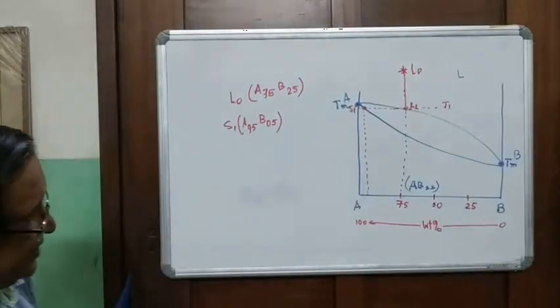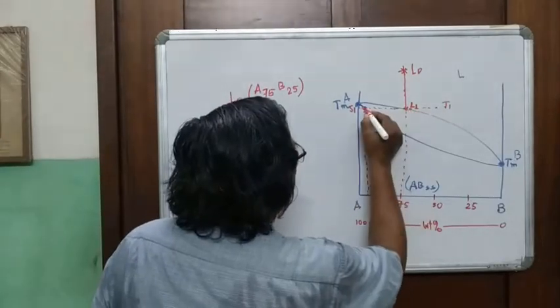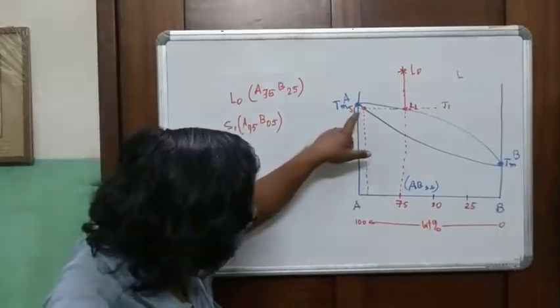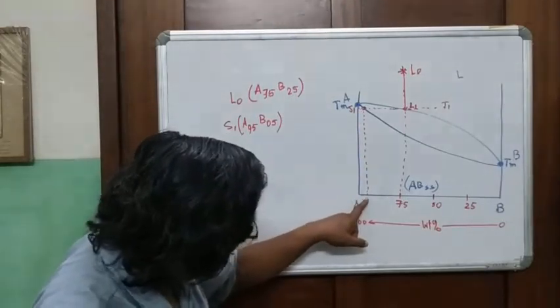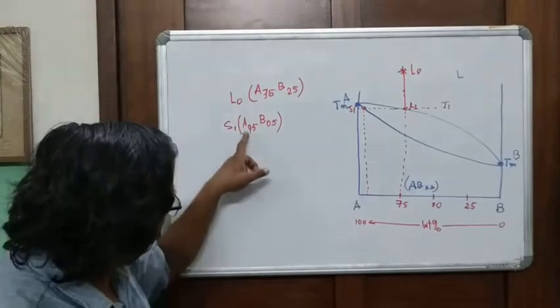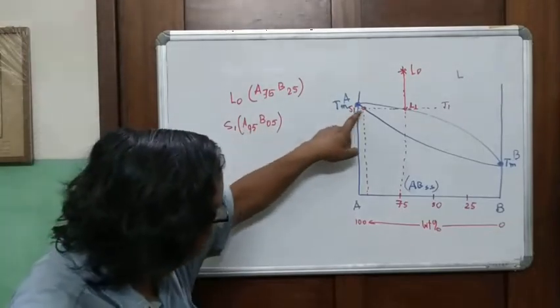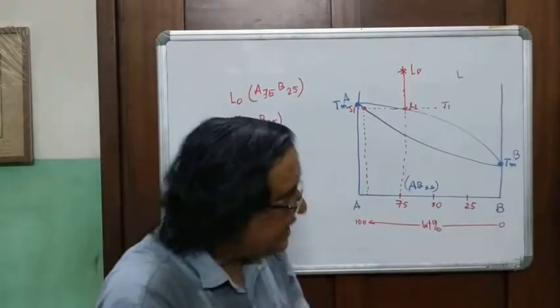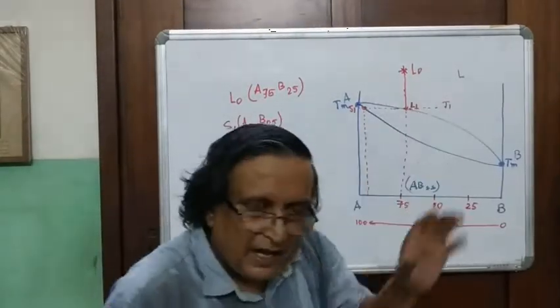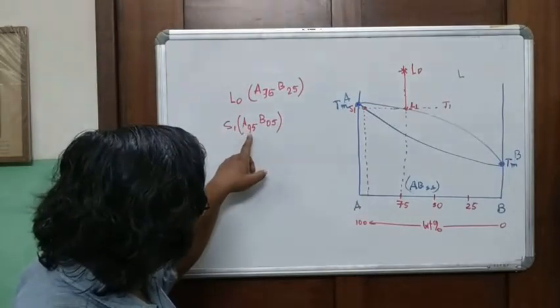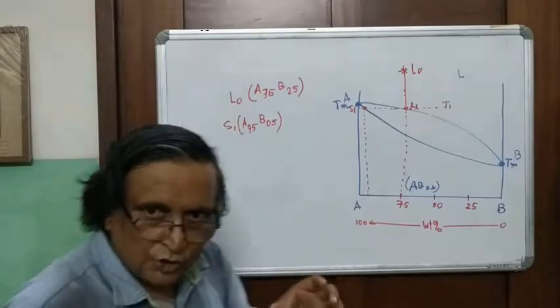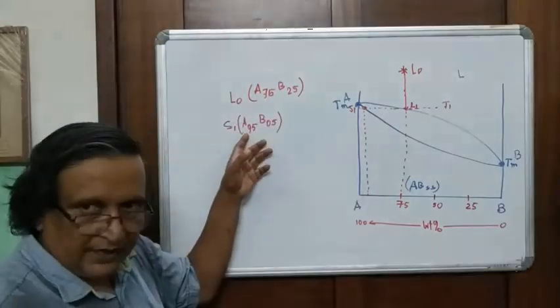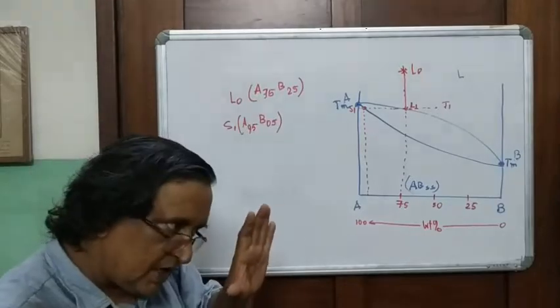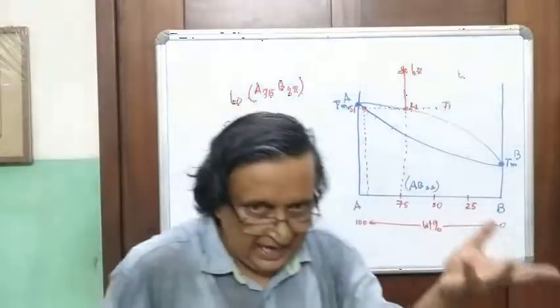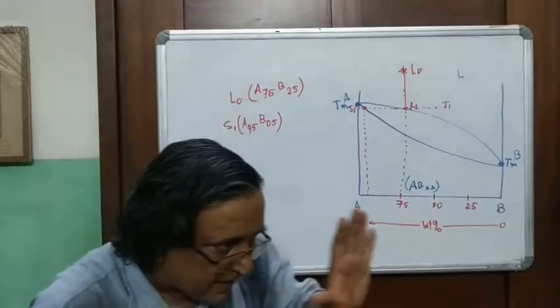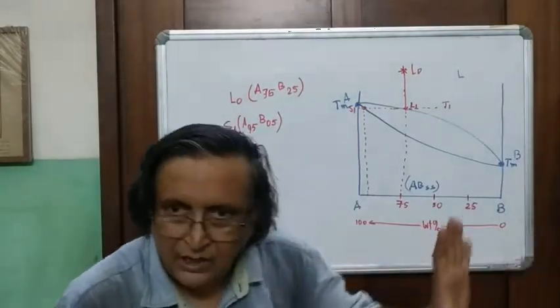Now once this happens, where you have a liquid in equilibrium with the solid solution, this solid will precipitate and will have a composition of A95 B05. As this solid is crystallized, obviously the melt has to move, because you see the solid has more A than the liquid. So once you crystallize this solid, the liquid composition becomes impoverished in A. So the liquid becomes enriched, or richer, in B.